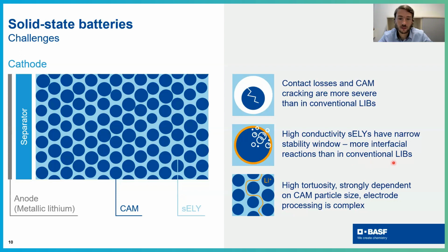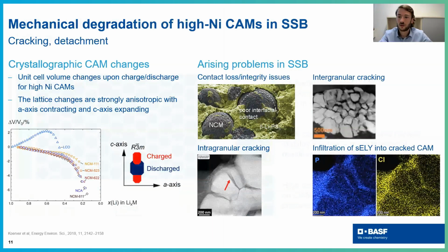And finally, you always have more issues related to the ion transport in solid-state battery systems because you have a tortuosity problem in the high loaded electrodes. And this problem is strongly dependent on the cathode active material particle size, which is not the case for conventional lithium-ion batteries. So here you also have to consider the particle size of the secondary particle. So a lot of things to consider, a lot of challenges, but let us start with the mechanics.